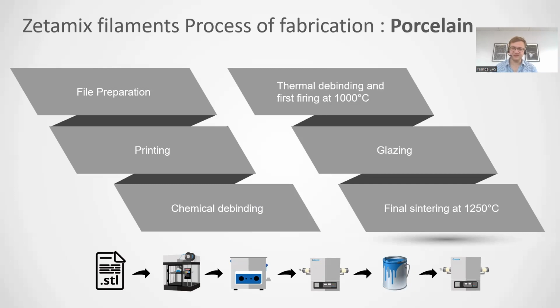This first sintering will give us what we call the part-fired part, or a biscuit, sometimes it's called, which is a porous ceramic. And with that porosity, we will go through a glazing, which I will detail later on, before doing the final sintering. So we add a few steps in the obtainment of the final part, but you will see that these few steps are really critical to get fine, nice looking porcelain.